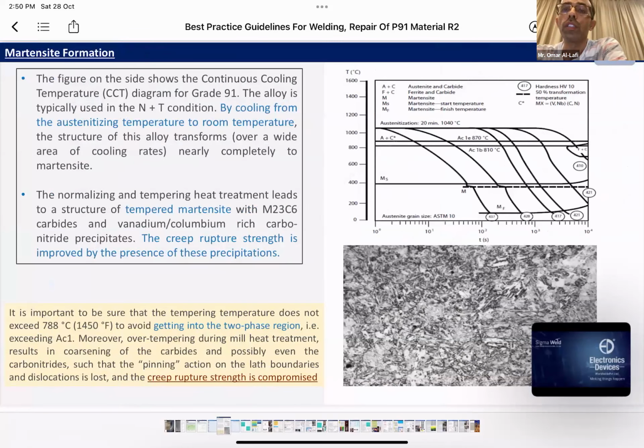And we'll go to martensitic formation. As I said, what gives the strength for this material is the martensitic transformation upon cooling. So during cooling from austenitization temperature to room temperature, the martensite structure will form upon cooling, and that structure is what is required in P91 material. So P91 material is not another low alloy steel. It's a different grade and should be treated as such.